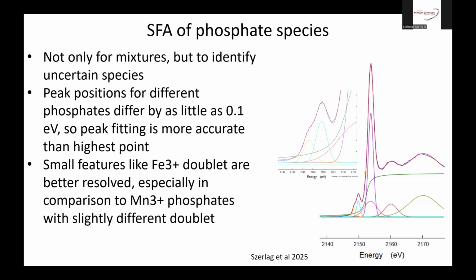So for sulfur, it's more of the broad brush, big details of what's where. And for phosphorus, the same tool is much more useful for teasing out the very subtle details, very small shifts of peak position and very small features. So that's all. Yes. And actually, one of them is fairly similar in position, but the other one is shifted over. So we've actually used that. If you have high enough quality data, we've used that to distinguish an approximate manganese-iron ratio for the phosphate. And so that's one of the more advanced uses.